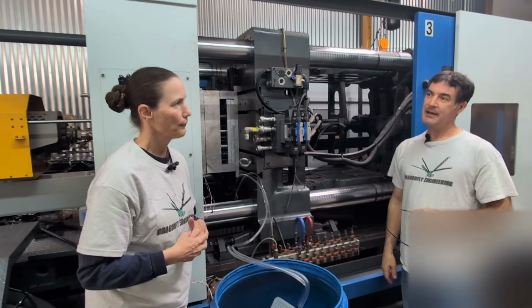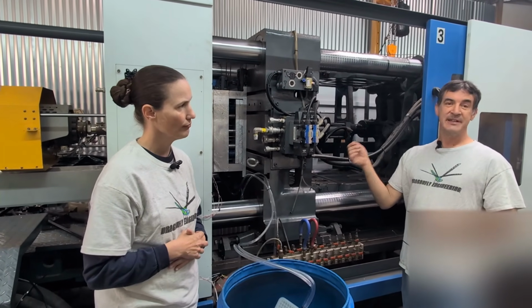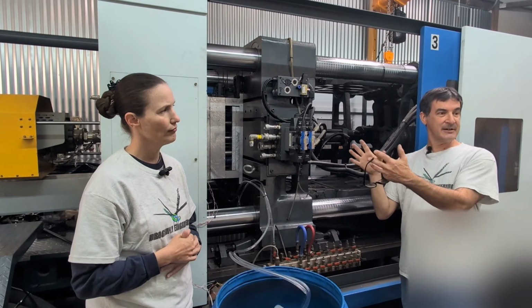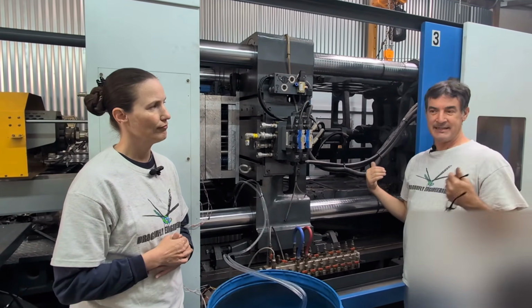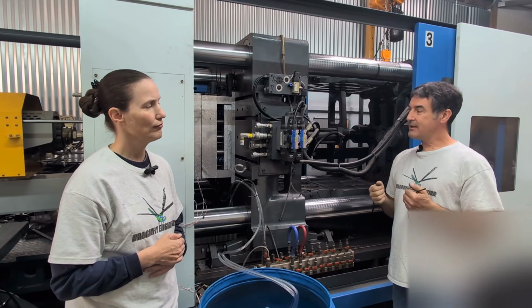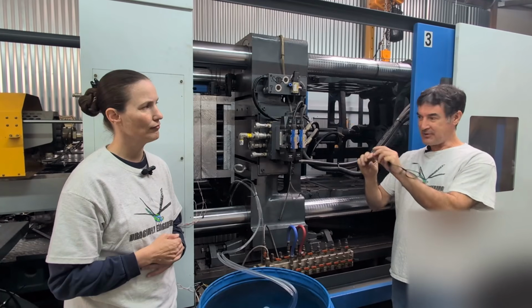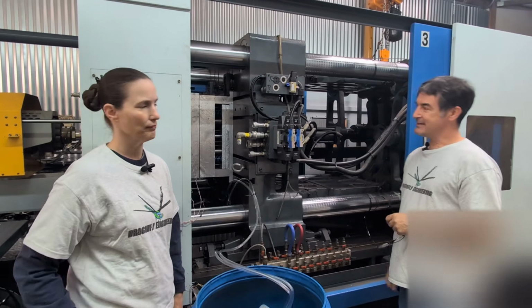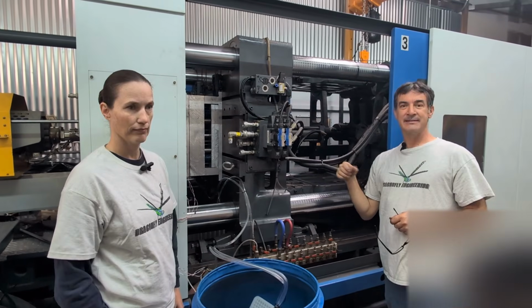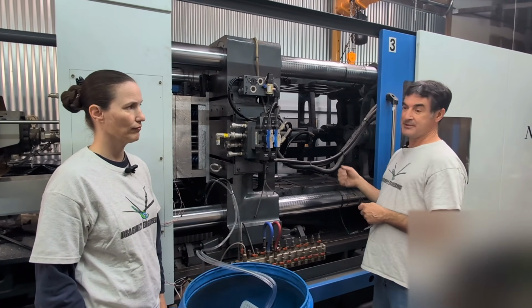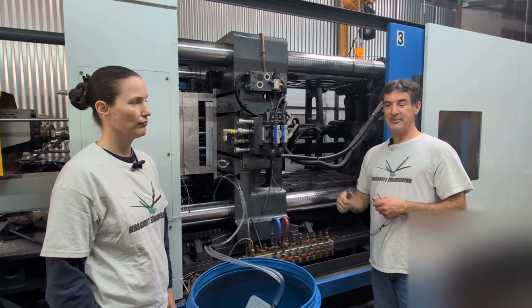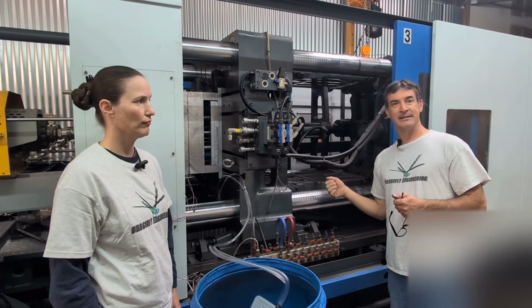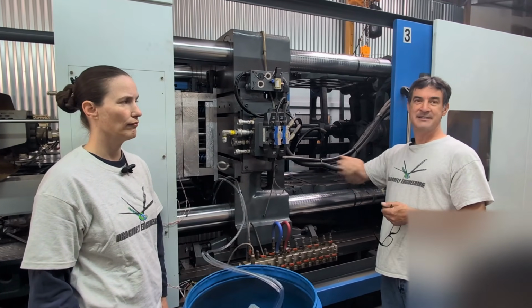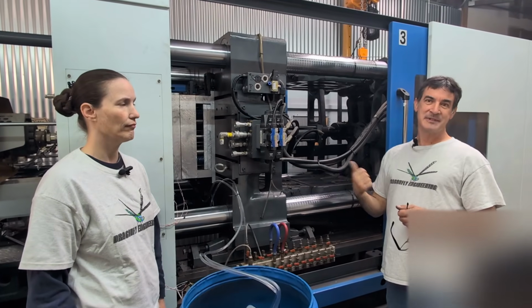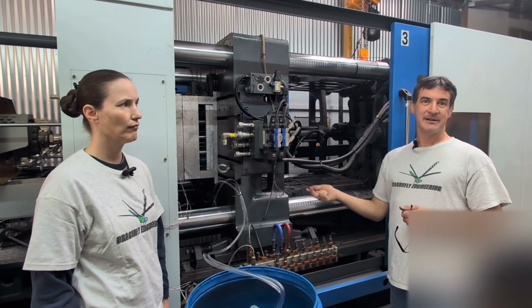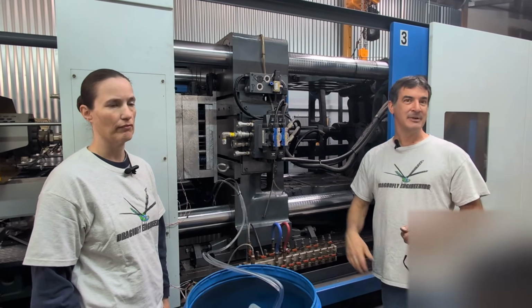Right. So other things to consider with the mold design would be the venting, because when a mold closes, it's full of atmospheric gas. But when you shoot the plastic in, and usually that takes about 1 second of time, all of that gas or air that's in the mold has to get out of the mold so the plastic will take its place. So there's also gas vents and things like that to consider in a mold design, which also play into the process parameters. If you have a mold that has trouble getting all of the gas purged out when the plastic is squirting in, then you need to slow down how fast your plastic is pushed into the mold. So again, mold design affects process parameters and quality of part and cycle time, which is also a key factor in production.